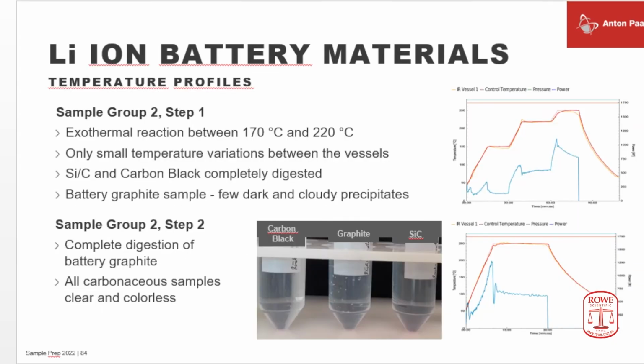But this is what you get to see at the end. Carbon black, graphite samples, silicon carbide. What do you see? Nothing. So that means it's destroyed. It's completely mineralized. You do not even find small black carbonaceous powders. So this is a photographic image after transferring the sample into an autosampler vial and diluting up to 25 milliliters.